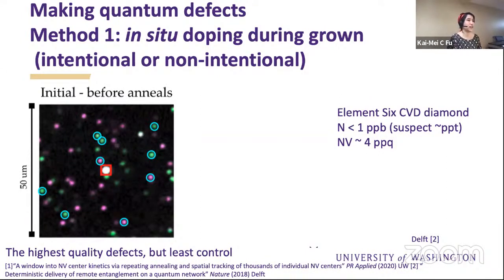So the first one is in situ doping during growth. And so here you can see a confocal scan of a bulk diamond substrate, and it's false color, where the color is actually encoding the polarization of the light that's being emitted in this case. And what you can see is that in this kind of slice of a 10 micron thick diamond slice by 50 microns by 50 microns, you can see a handful of defects.